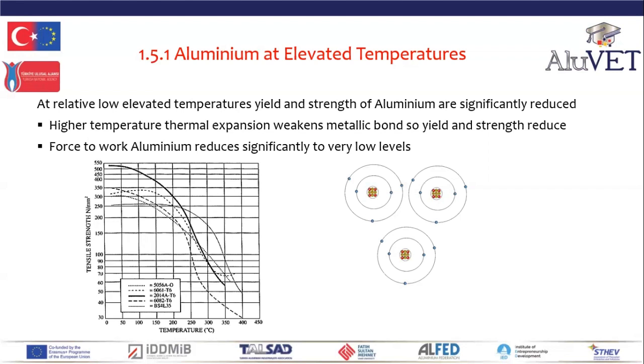Now, extrusion and hot rolling temperatures are higher than the recrystallization temperature. The deformation forces, the forces required to reshape hot worked aluminium, are dramatically reduced to perhaps only 10% of those required at room temperature. So at a hot working temperature, we require low forces. We can achieve very high deformations.